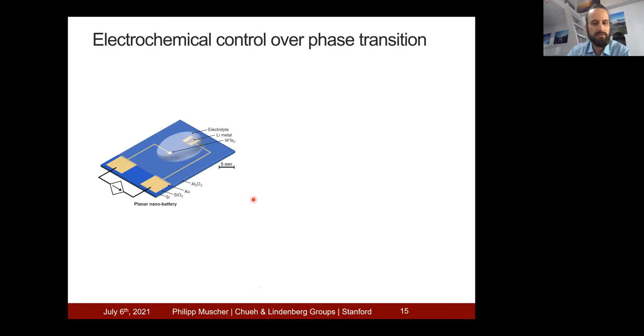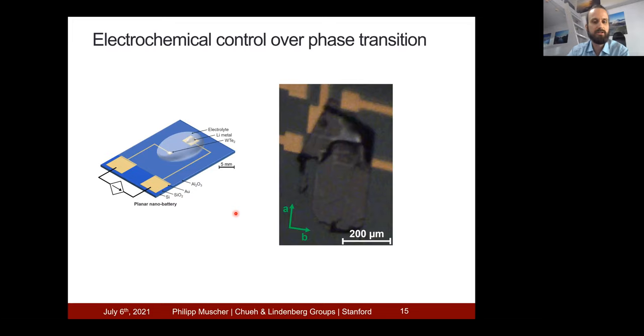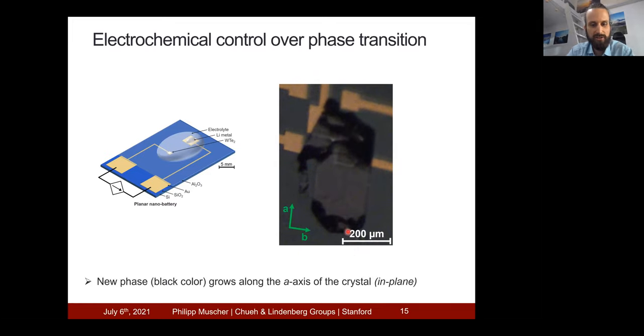So now that we have this working system, we can look at how a flake evolves as lithium is being inserted in it. So let's look at these optical images. You can see during lithium insertion, the flake turns black, and that black front is moving in from top and bottom, which corresponds to the in-plane A axis of the crystal, which will become important later on. So you can see the whole flake is becoming black. So this is a proof that the ion insertion in the single flake system is working.